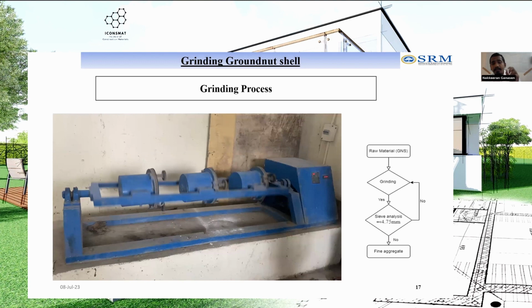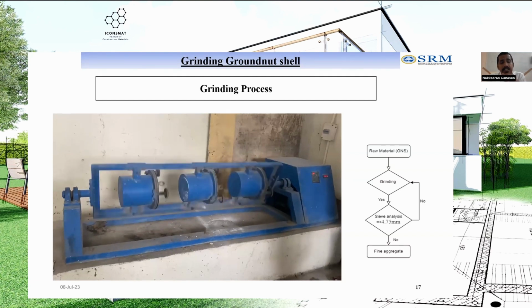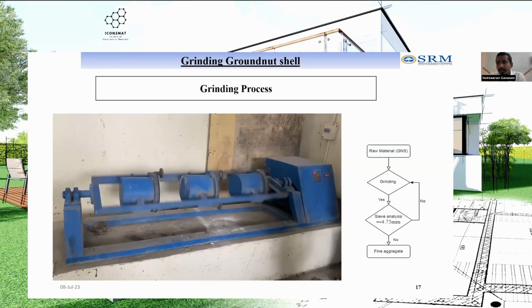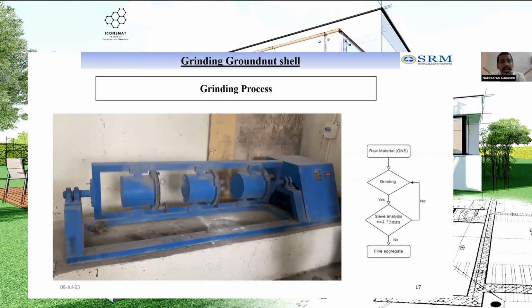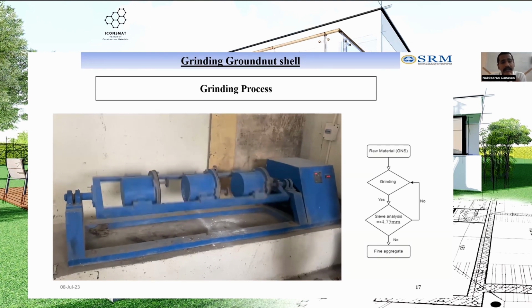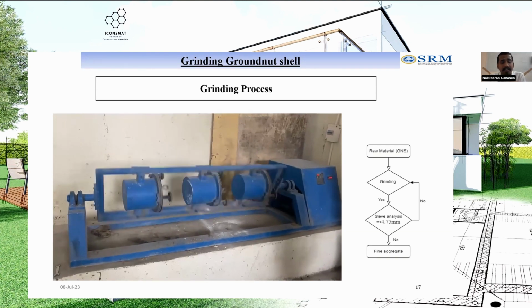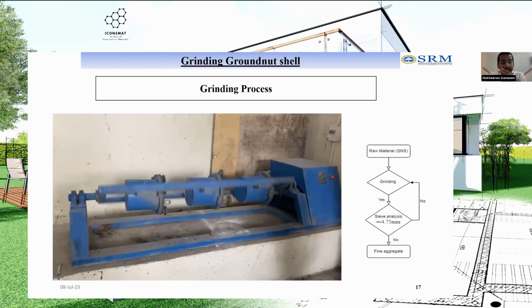This is the basic process. First, we collected the GNS materials and we need to grind them because the particle size is very big. When using it like this, we cannot compress easily when making compressed bricks. So first we need to grind the materials so that the fine aggregate will be very fine. We grind the materials using this miller machine. It rotates for 10 minutes and we stop it, and we rotate it again for 10 minutes and stop it, and we get this fine aggregate as fine particles to replace the fine aggregate in the brick as a waste material.